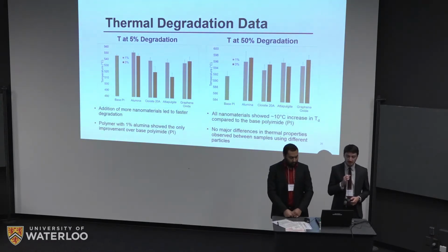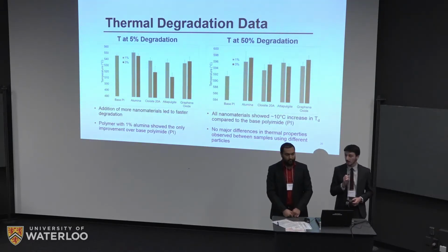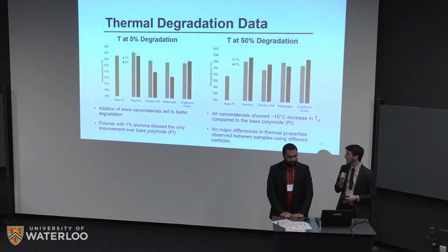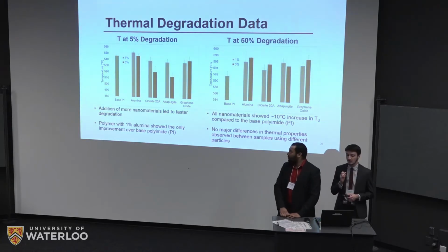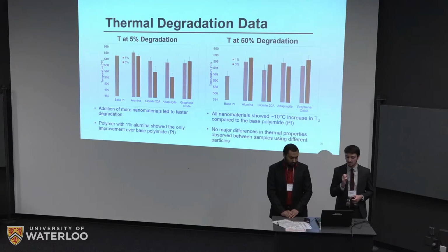What we noticed is for at 5% degradation, there was some improvement when we added alumina nanoparticles to our polyimide when we compare it to just the plain polymer. But this effect is not particularly consistent when we look at all the other materials. It seems that some of the onset temperatures were pushed to actually a lower temperature with some of the nanomaterials.